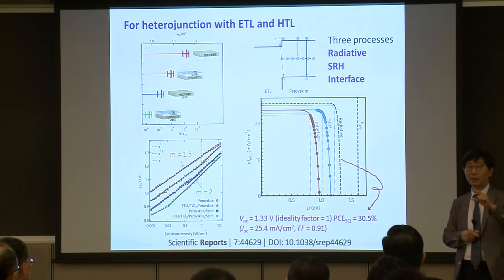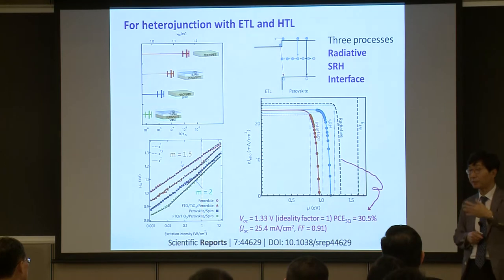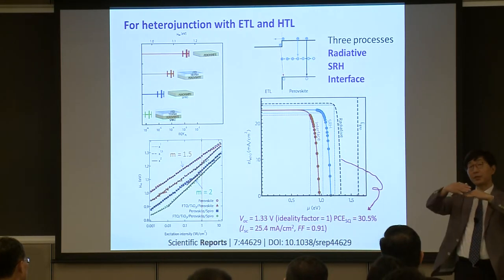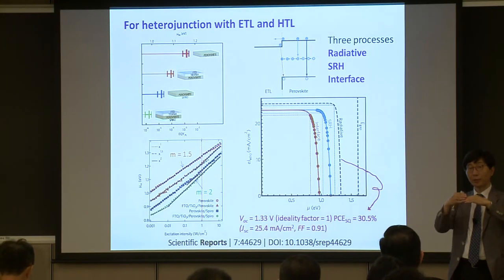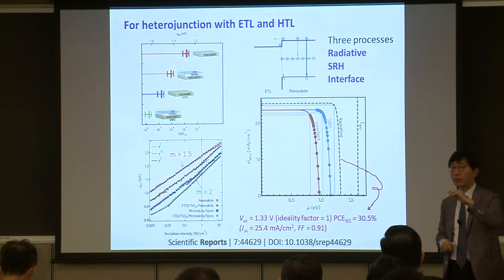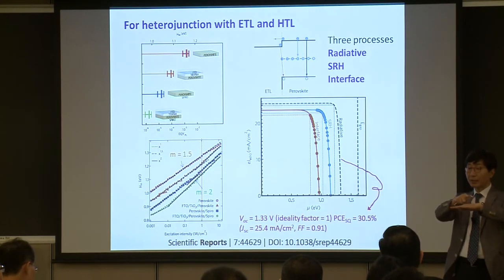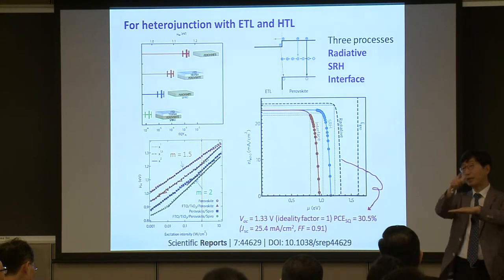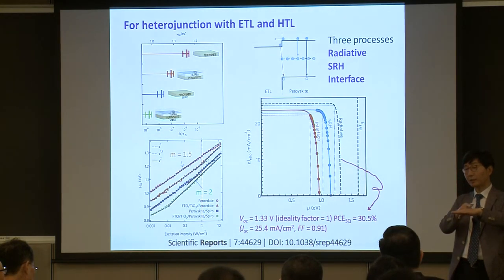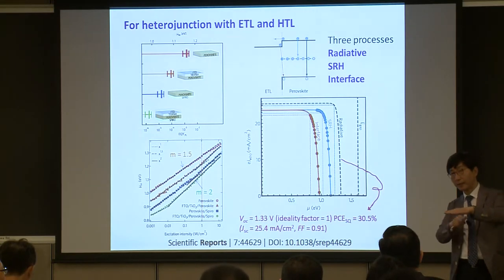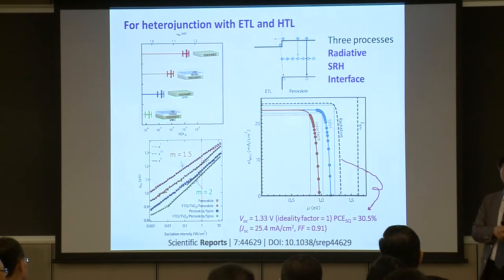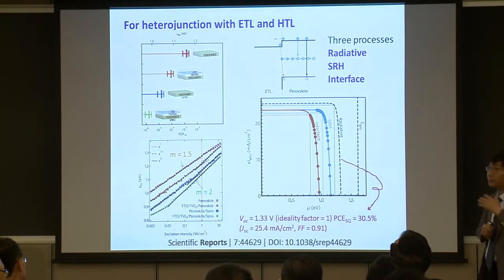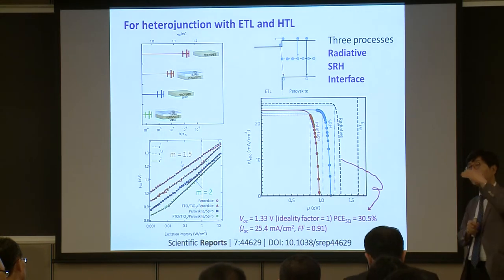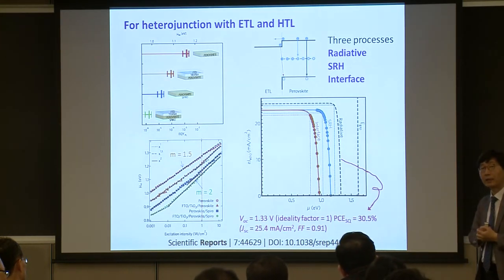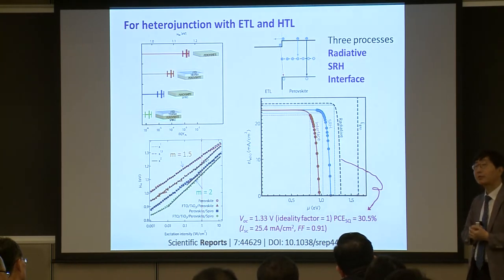Because our perovskite has the heterojunction structure, titanium oxide, tin oxide, PEDOT:PSS, whatever, and then this surface is mismatching with the perovskite layer. So probably the selective contact surface is very important. Also, the region of the perovskite very near to the ETL or HTL is very important. So if you manage well the interface between the perovskite and ETL or perovskite and HTL, you can achieve the higher efficiency.